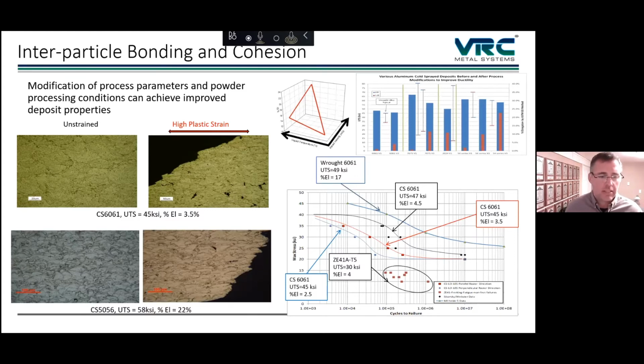This also translates over to fatigue performance, as you can see on the right-hand side of the page here, where going from the blue to the red to the black curve, we're going from 2.5% elongation to 3.5 to 4.5. So you can see the increase in fatigue performance as you get rid of a lot of those interparticle defects that are present in the material.